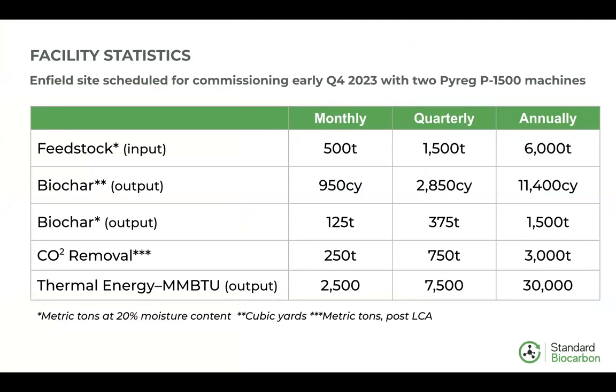So here are some basic facility statistics that we're expecting once we're running continuously. We'll be producing roughly 1,500 tons of biochar annually with an average bulk density of 12.5 pounds per cubic foot. We expect that to come out to around 11,400 cubic yards annually. And the bulk density is subject to change depending on the moisture content of the biochar, which can be altered depending on customers' desires, as well as particle size. We're thinking about putting into place some post-processing equipment that can mill the biochar down to finer particle sizes, which would increase that bulk density, obviously.